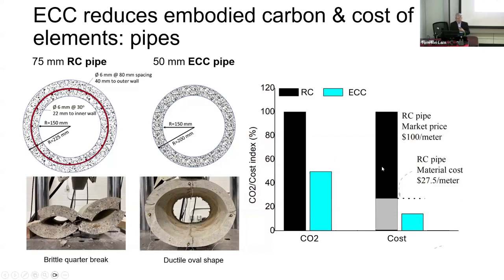Amazing, we were surprised. Now, what I really want to show you is that if you compare the carbon footprint of these two very simple structural elements, if the concrete is 100%, then the reinforced concrete is 100%. The ECC pipe is reduced to about half of that. Okay, how is that possible? You say, how is that possible that you have a material that is supposed to be less green, even if we say that it's equal in greenness, at least you get a pipe that should have the same amount of carbon emission, but you get 50% off. Well, we remove the steel reinforcement, we reduce the amount of material required.